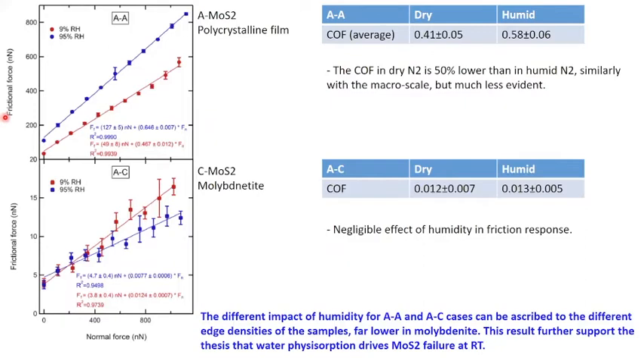In order to do that with AFM, what you have to do is to measure the lateral force as a function of the load. Of course, the slope of the resulting curve represents the coefficient of friction. So we did this experiment for the amorphous coupling, so our tip against the polycrystalline film, and in the case of the amorphous-crystal coupling, so our tip against the molybdenite. And we did the experiments in absence of humidity, the red curve here, and in presence of humidity, the blue curve. And the results after averaging all the data are reported in the table.